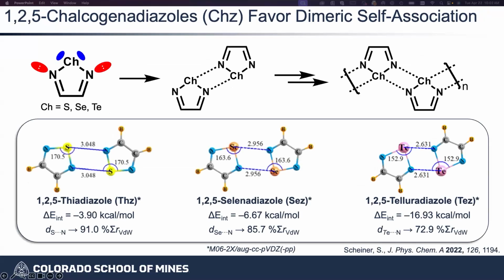What element do I use? If I go from sulfur to selenium to tellurium, the dimerization strength gets basically exponentially stronger. And it turns out that this strength, if you do the same calculation with basically urea dimerizing, is stronger than urea dimerizing through a hydrogen bond. So these are very strong non-covalent interactions. And so